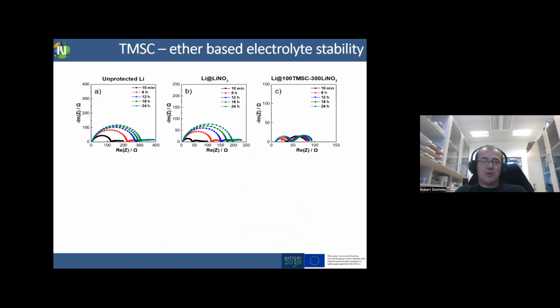And to understand this property now, we employed impedance spectroscopy, and we assembled a symmetrical cell, lithium-lithium, first both lithium unprotected with the Celgard separator and lithium nitrate inside the electrolyte, and then with both lithium protected. What we can see is that there is a huge evolution of the impedance within 24 hours, which creates some problems with the passivation. So this tail is also growing. While here we see, in the first 10 minutes or maybe the first hour, some shift, but then this shift is stabilized. And that suggests that there was a formation of a stable passive film after assembly.